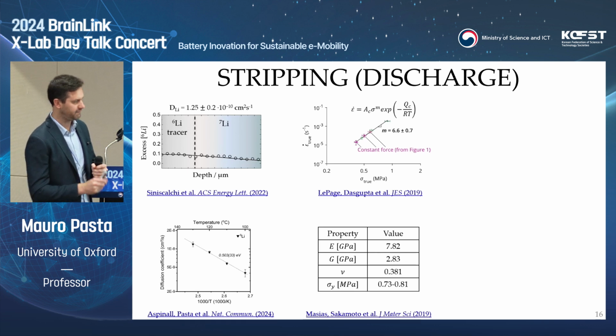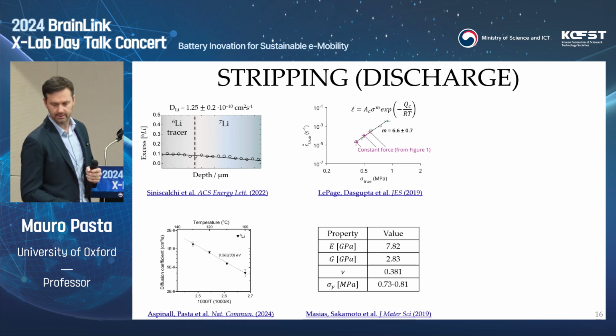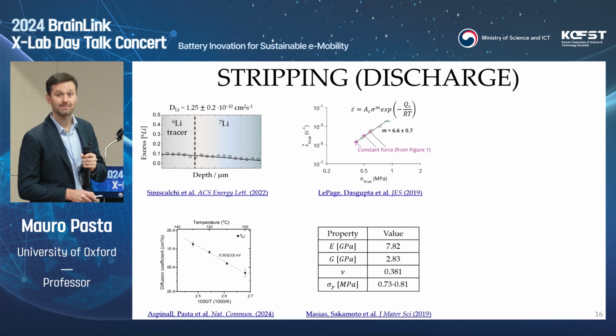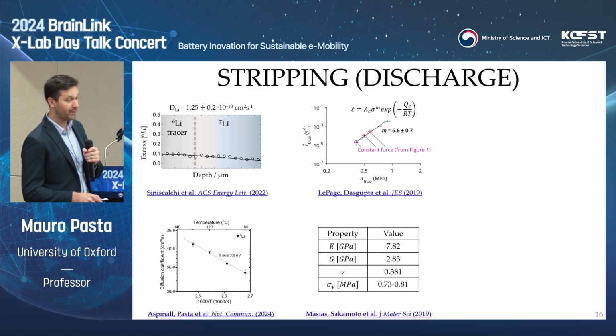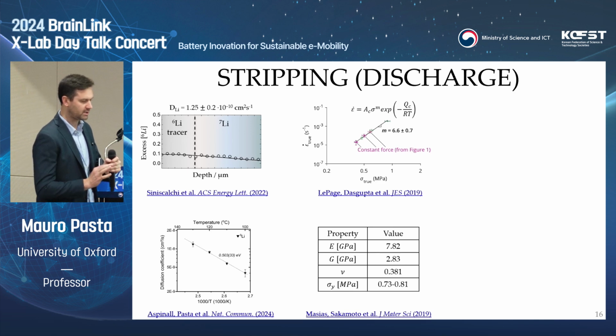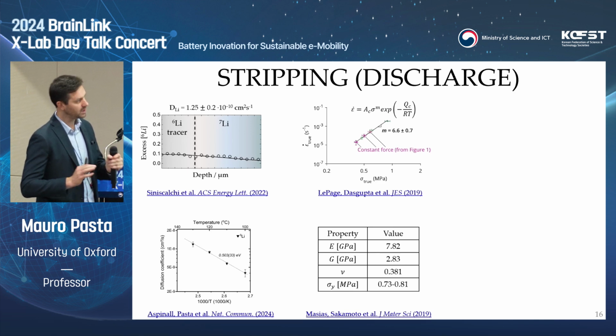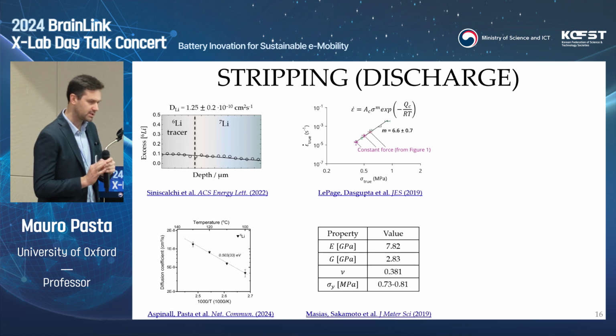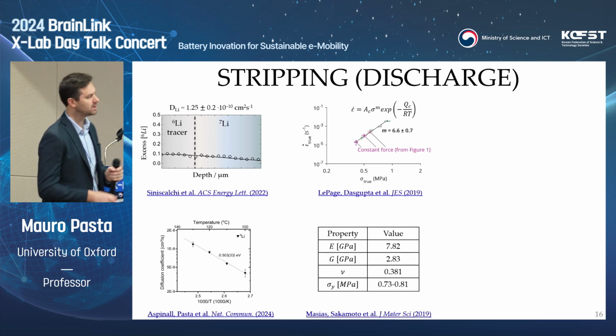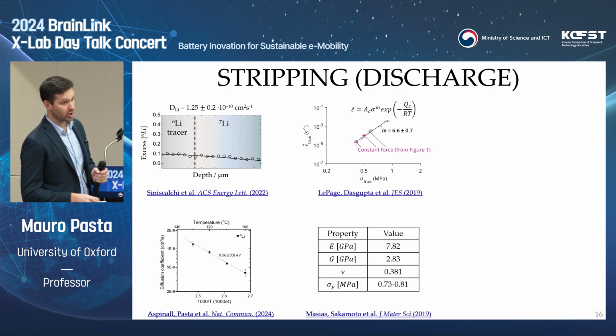so the stress you need to apply to plastically deform lithium, is quite low. It's in the order of 700 to 800 kilopascal. So you can basically squash it by applying pressure and therefore maintain contact that way. Also, at room temperature, because of the low melting point, you have quite substantial creep, which is a permanent deformation of a metal when it's subject to a stress. In a normal metal, you apply stress and the strain will go to zero quite rapidly. In the case of lithium at room temperature, when you apply that stress, lithium keeps flowing, basically. So you can rely on pressure and temperature to maintain the contact.